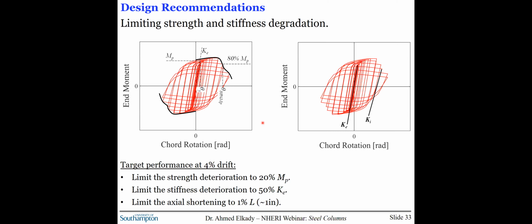Specifically, our target performance in this case was at 4% drift, where we need to limit the strength deterioration to 20% of Mp, limit the stiffness deterioration to 50% of the initial elastic stiffness, and also limit the amount of axial shortening to 1% of the column length, which is roughly about 1 inch.